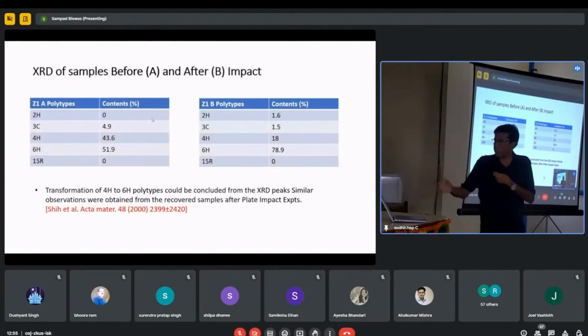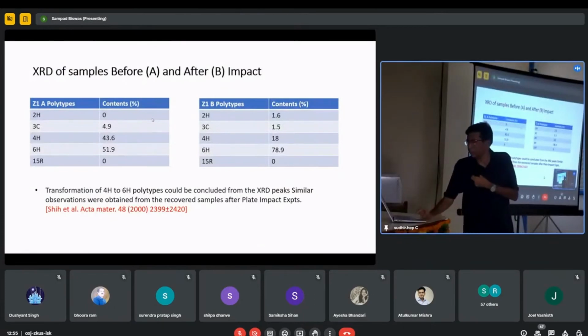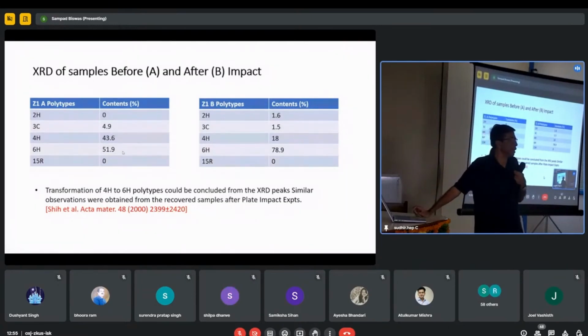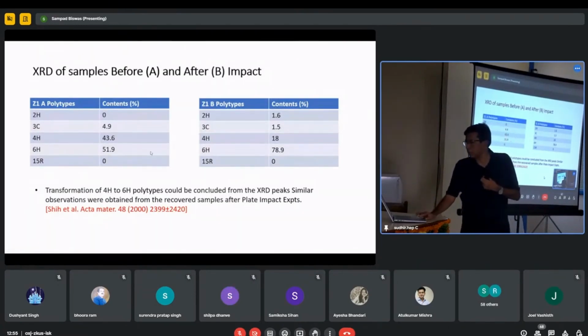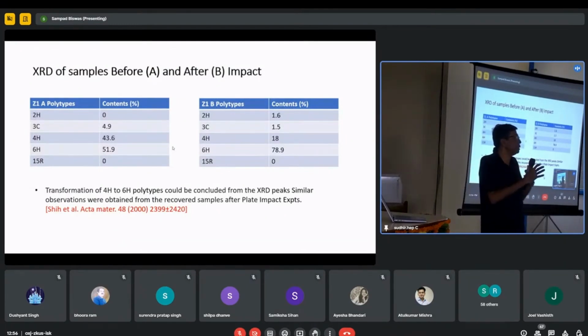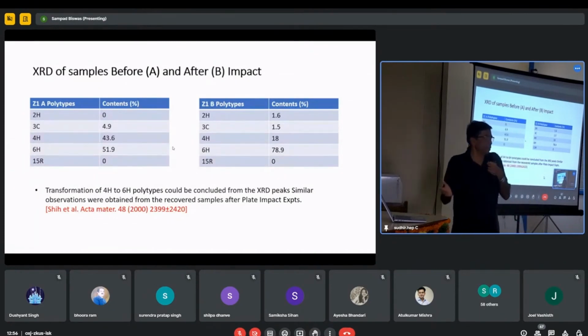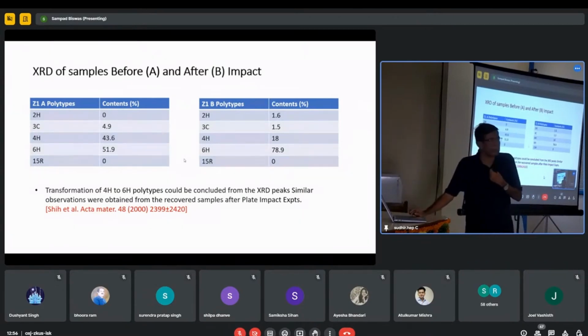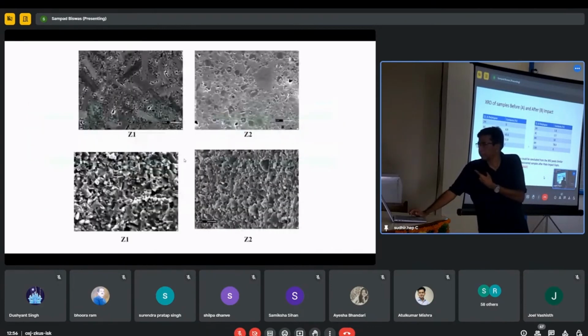Now we have analyzed the XRD samples after the impact. We can find that initially we started with 51.9% 6H variety. It changes to 78.9%, while the 4H is reduced as well as 3C is reduced. That means these phases have transformed with the help of the shock wave to the 6H variety. So that is a very important observation we could find out. And this observation was also made by some people earlier, in the year 2000. So this is in the case of another variety of silicon carbide.